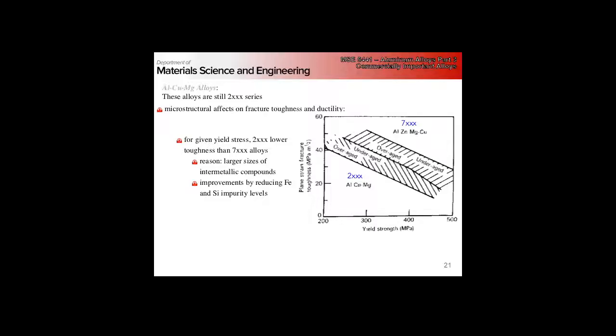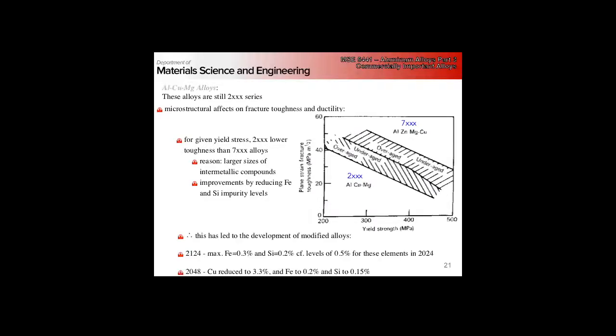This is due to the larger intermetallics that tend to form in 2000 series. We can again make improvements by reducing the iron and silicon. Iron keeps coming up as a huge problem, so we try to take care of that by making some modified alloys.